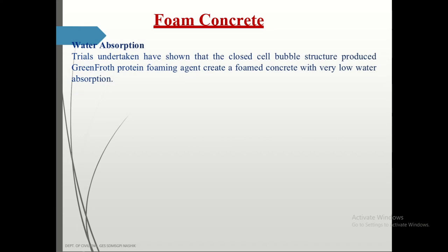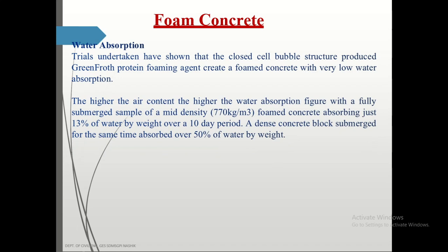These are some properties of foam concrete: water absorption. Due to cellular structure, bubble structure, it's very low on water absorption. Okay, due to high air content, the water absorption rate is higher. A dense concrete block submerged for the same time absorbs 50%, means our normal concrete block absorbs 50% water in 10 days, whereas foam concrete absorbs only 13%. So you can imagine how low the water absorption is.